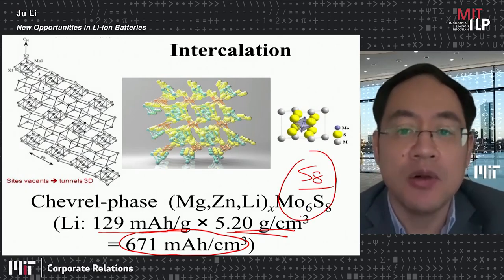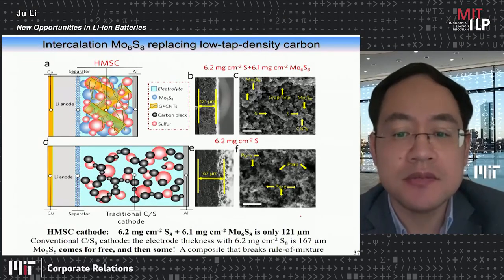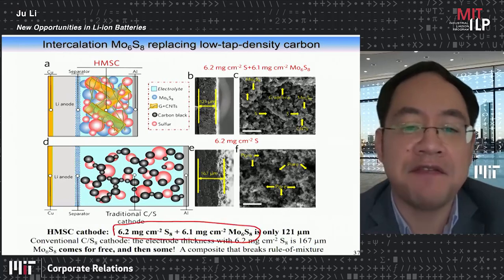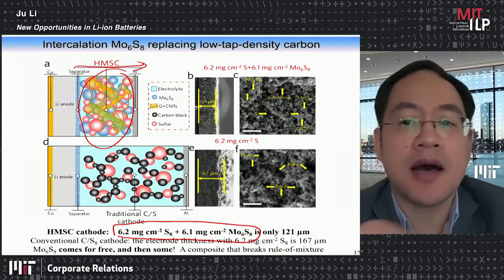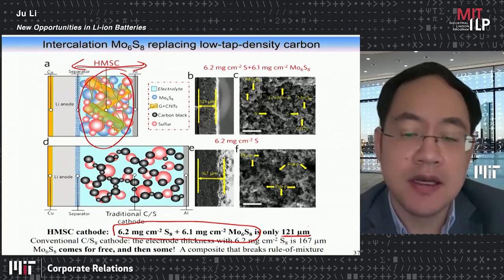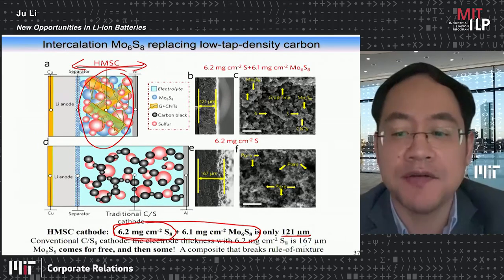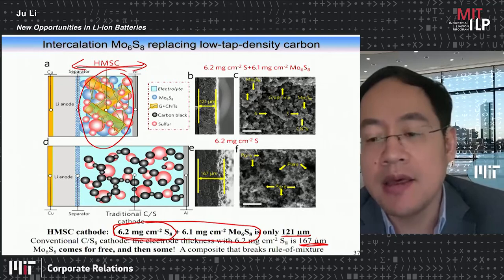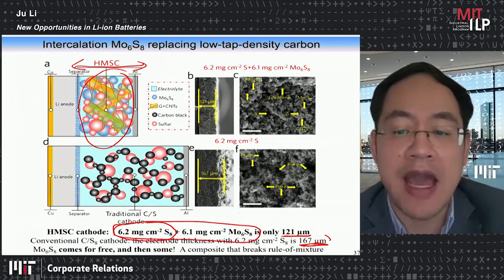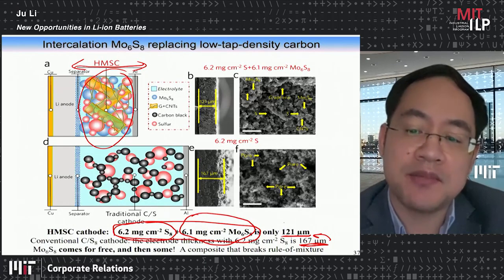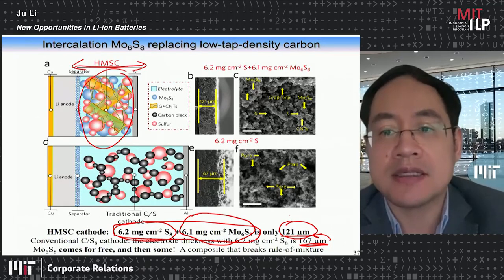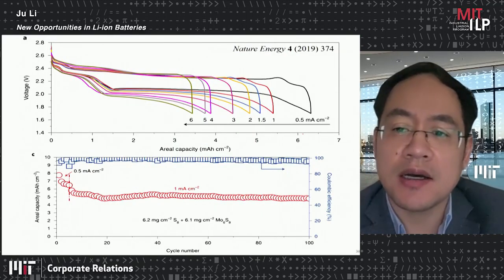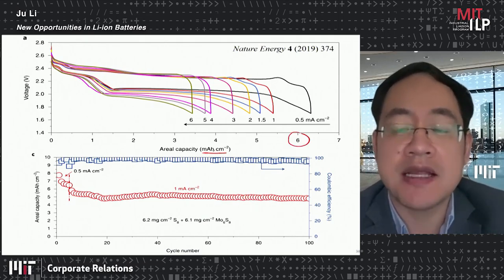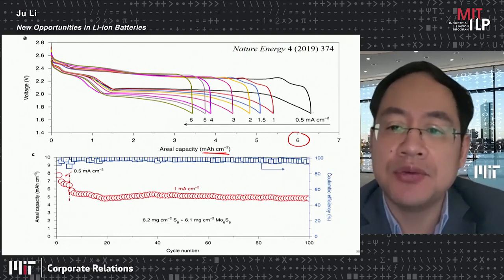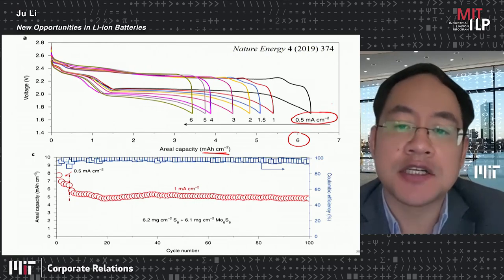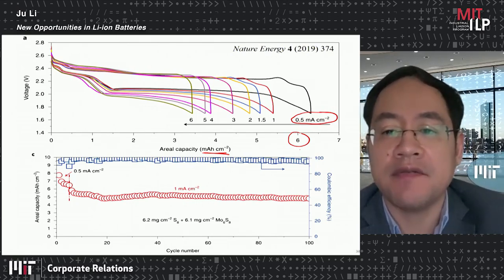is able to achieve a very high loading. So we can get something like 12 milligrams of this 50-50% mix, and we can do a hard compression on this composite to only 120 microns. In contrast, if you just use this much sulfur, you cannot do hard calendaring, and you can only have a thickness which is actually thicker than this. So we actually have this extra material, but still even lower thickness. And so we can get in the system 6 milliampere hour per centimeter squared area capacity if we do something like 0.1C charge discharge. And this is a very high loading system.